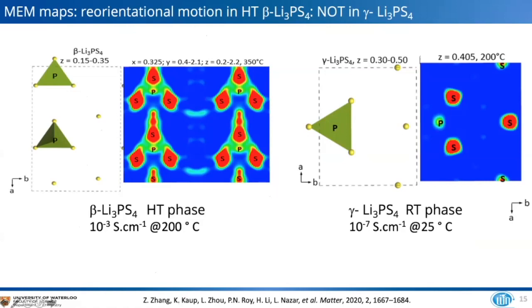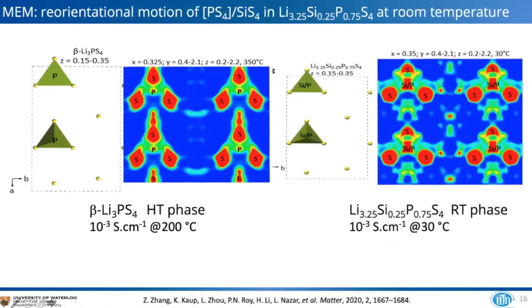the MEM map here shows that there is absolutely no rotation whatsoever, whereas you can see that rotation in the high temperature, the so-called beta phase. At 200, this data was actually collected at 350, but you can definitely see the onset of that rotation. And if you compare that with the silicon substituted form, you can see the rotation is very evident in this silicon phase at room temperature, which also has about a 1 millisiemens conductivity at 30 degrees centigrade.